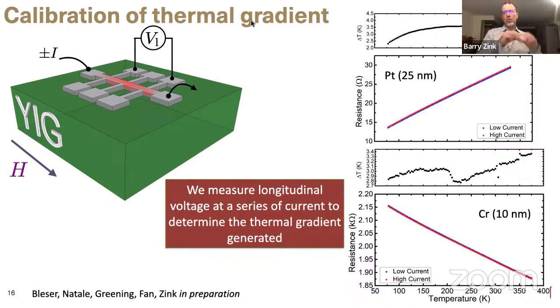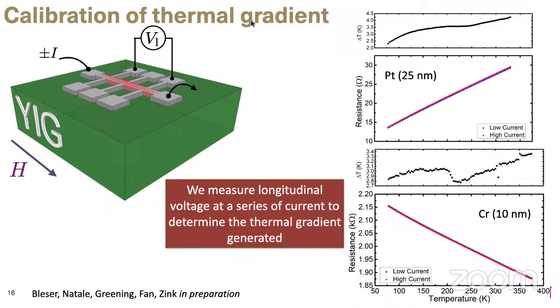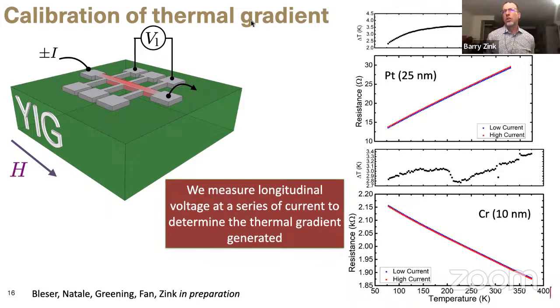So we do choose a strip width that will give a reasonable amount of heat generated for the current that we apply to it. So it's a relatively narrow strip with nice large pads out at the sides to actually bond to. This cartoon is actually the correct relative sizes, because I believe I made that cartoon by copying the actual lithography file and then tilting it on its side. I see. I think a typical size would be like 800 micrometers by 10 micrometers. Ours are a little narrower than 10 micrometers, I believe, but not really different than what you said.